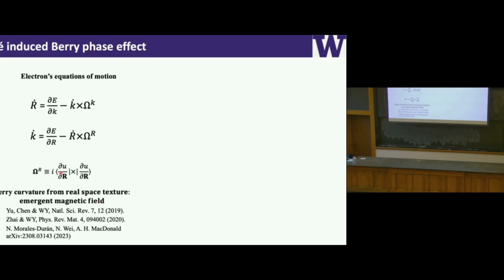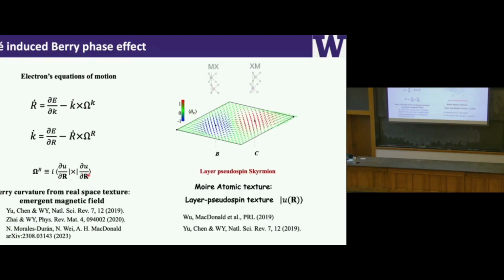It's the derivative of the wave function u with respect to the position r. So if I give you a homogeneous crystal, then this derivative of u with respect to r actually vanishes. What it means is that in a single crystalline system, there's no Berry curvature effect in real space. But the situation changes in this moiré superlattice. As you go from this layer pseudo spin, say, pointing up to the layer pseudo spin pointing down in real space, the pseudo spin must rotate, forming these pseudo spin skyrmions, as Allan pointed out.